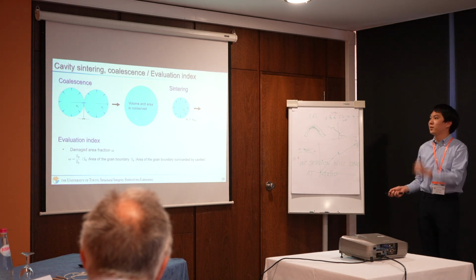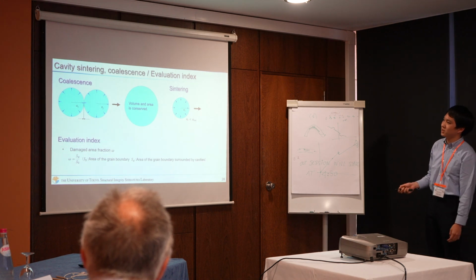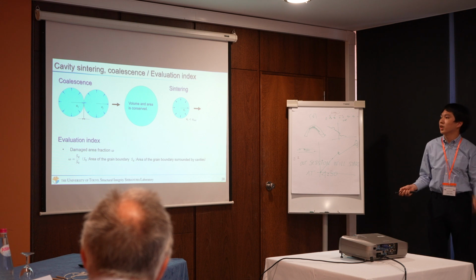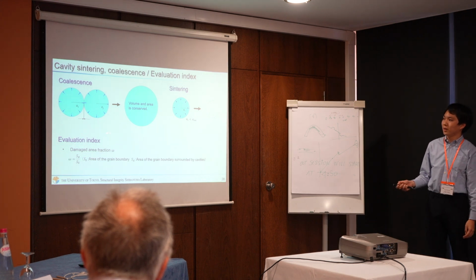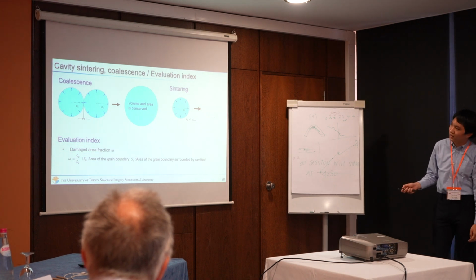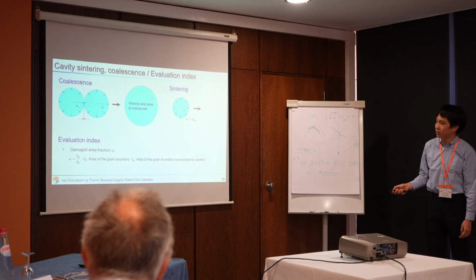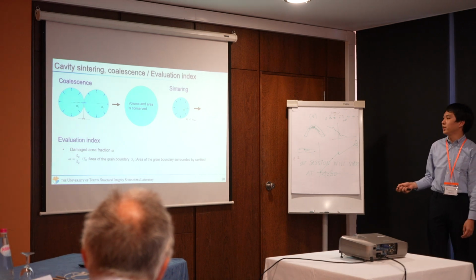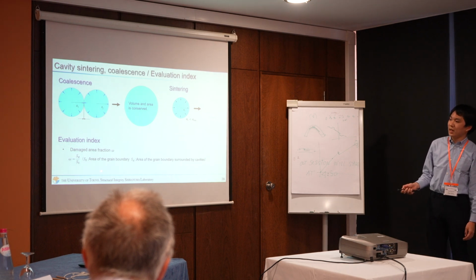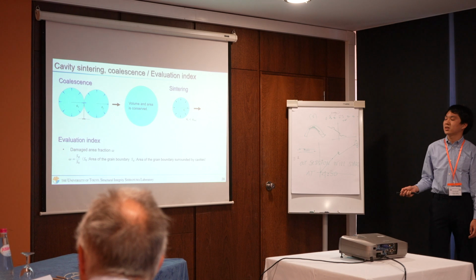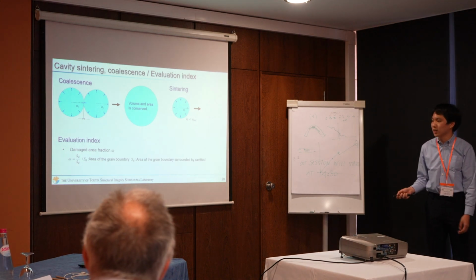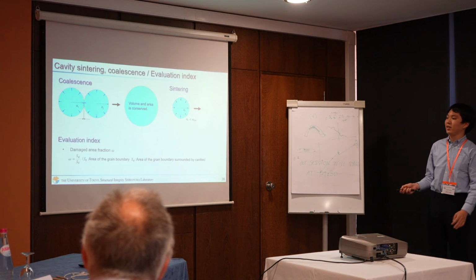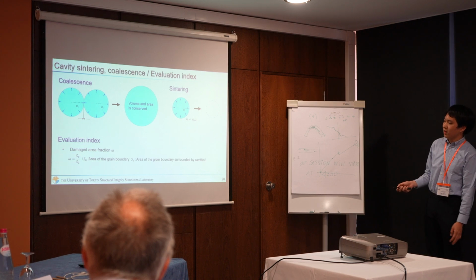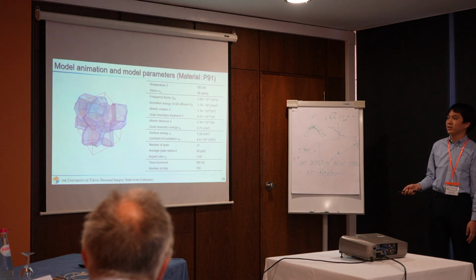This is the criteria of cavity sintering and coalescence. Cavity coalescence occurs when the 2 cavities overlap, and cavity sintering occurs when the radius of the cavity becomes smaller than the initial one. Then the damage area fraction is adopted for the evaluation index. Damage area fraction is a ratio of how cavities surround the grain boundary.